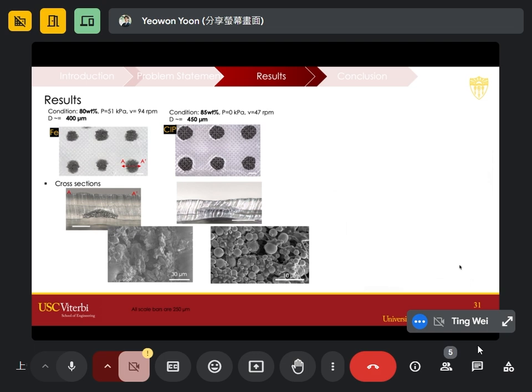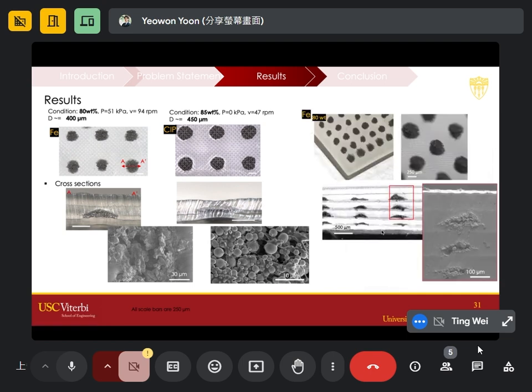The cross-section of the shape looks like a very conical structure, and this conical aspect ratio increases with the viscosity. Then you can look at the morphology of two different types of iron powder. And then the one sandwich layer goes on and on to create multiple layers of the structure. Here is the iron powder 80% printed on 5 different layers. So what do we do with this?